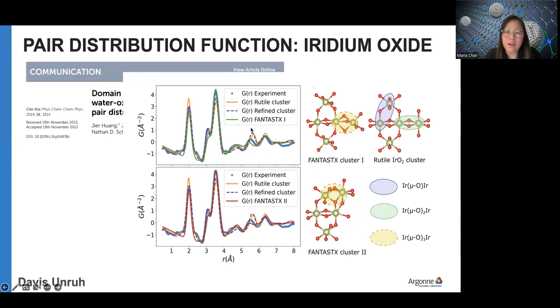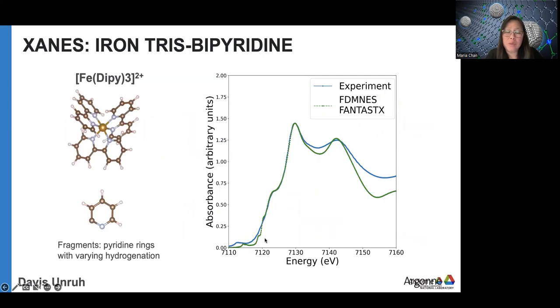Most of that was waiting for computer time to run, and then it found a slightly better fit in terms of chi-square. It also discovered some structures that wouldn't be intuitive for modelers, such as this 3 oxygen bridge between the 2 iridium atoms. So we find that promising. In X-ray absorption, the fidelity of the simulation is always a problem. We never get as good with XAS as with many other things, but still, because there's a severe constraint with DFT on the structure, we were able to find this transition metal complex using an XAS that only roughly matches.